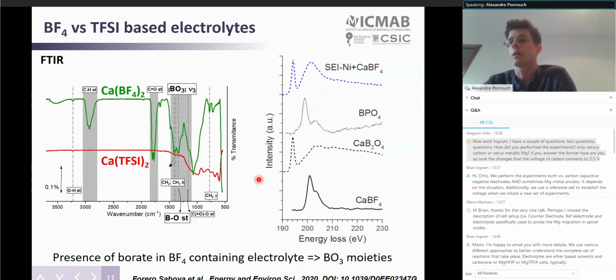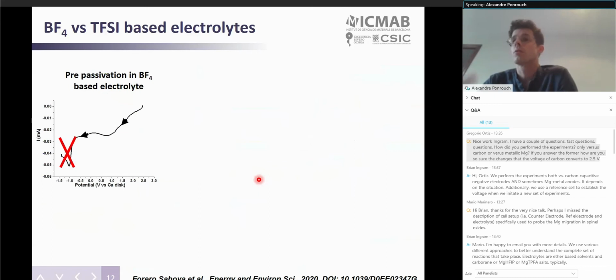So we think now these are part of the constituents of the passivation layer that allows the divalent cation mobility. To try to assess the fact that this passivation layer chemistry is key for achieving plating and stripping, we performed this simple test.